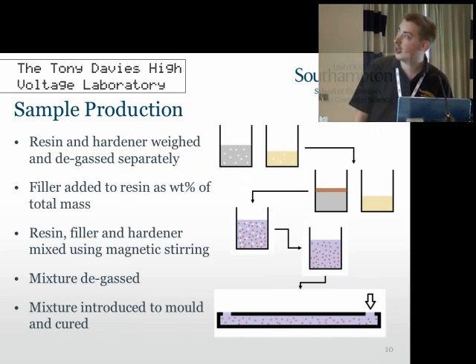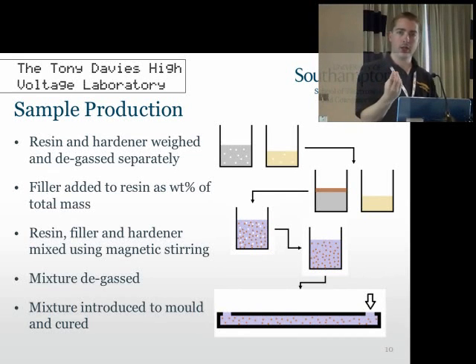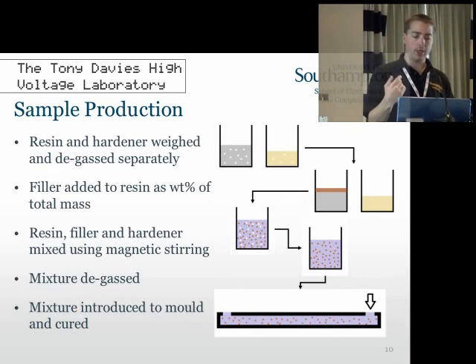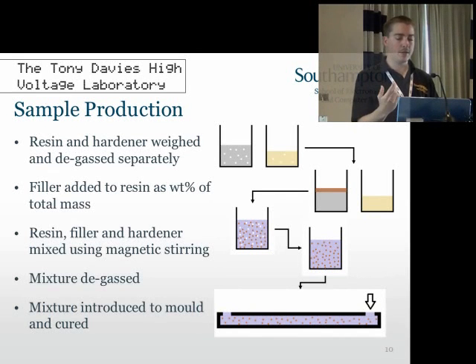Okay, so just a quick mention of how we make samples. We weighed out the resin and the hardener separately, degassed them to make sure that there aren't any air pockets inside. We then added the filler to the resin because it's more viscous. It will hold in suspension once we disperse it. We then mixed it all together, just using a very basic magnetic stir.